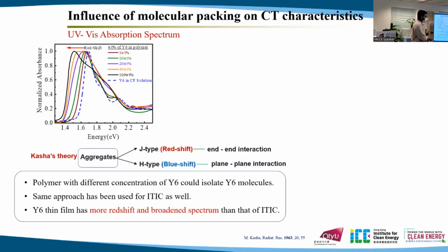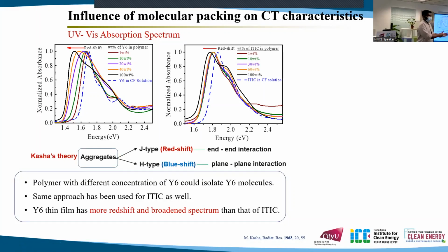And there is also a spectral broadening. There is also a small blue shift we can see. We used a similar approach for ITIC as well, and it worked. ITIC also shows redshift when we increase the concentration of ITIC in the polymer matrix. So what is happening there? It is based on Kasha's theory.